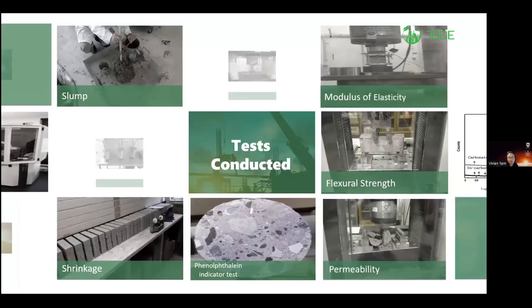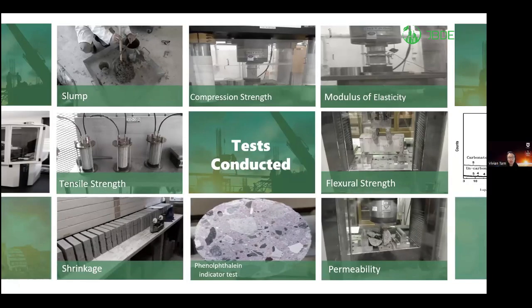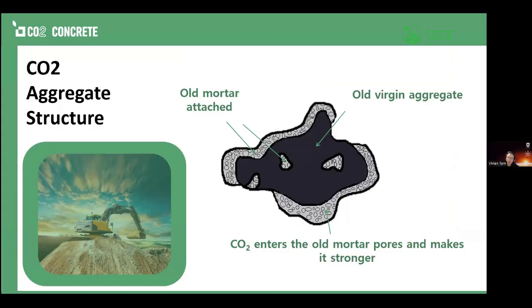In the last few years in the laboratory, we have done any kind of test that you can imagine, not only aggregate tests, but also concrete tests. We have done the physical and mechanical properties, but also some durability tests and also the chemical behavior. You may ask me how exactly it works in terms of the recycled aggregate and the carbonation process. Because it is a recycled aggregate, it not only has the old virgin aggregate, but also has cement mortar attached as well. Those are the weak components in the recycled aggregate. That is also the reason why the strength is reduced, because of the old cement mortar. But while we are carbonating the recycled aggregate, the carbon dioxide reacts with the cement mortar to help make it stronger.